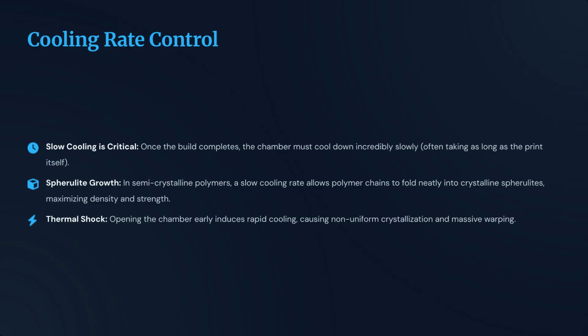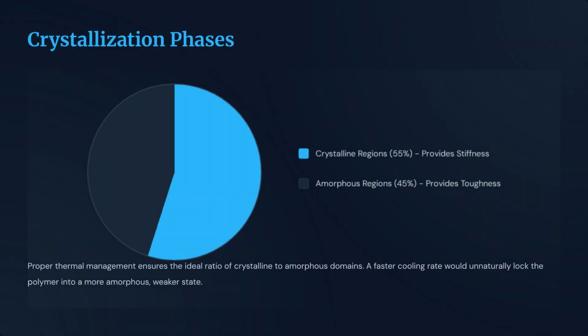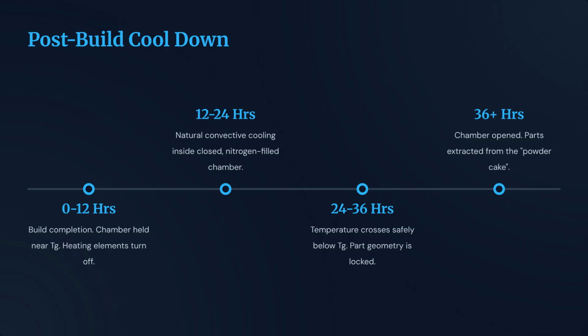Cooling is just as critical as heating. A slow, controlled cooldown allows the polymer chains to fold into dense, strong crystalline structures, while rapid cooling leads to thermal shock and warping. This management ensures the proper balance of crystalline and amorphous domains. Proper cooling prevents the polymer from being locked into a weak, amorphous state. The post-build cooldown follows a precise timeline, from the initial heat-off phase, through natural convective cooling, until the geometry is finally locked and the chamber is ready to be opened.